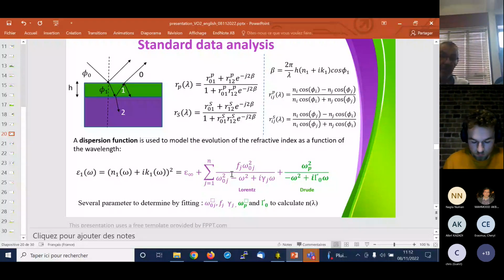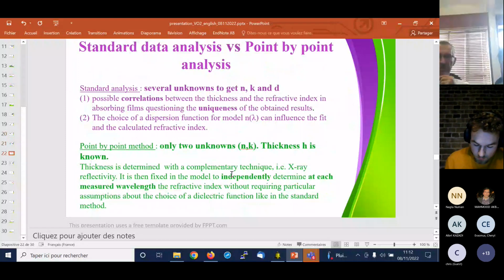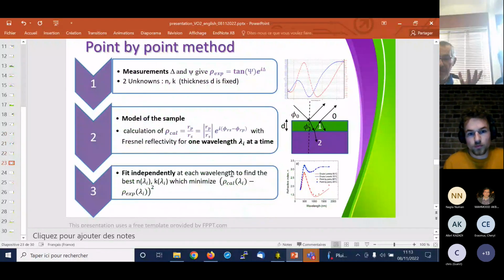And so the story which was pointed out by one of the referees, when we wanted to publish this paper, the referee said, well, you should not do that. You should do the point-by-point method. And the point-by-point method is indeed a very good method because you don't need to describe how the index of refraction is changing as a function of wavelength. You just have 2 measurements, delta and psi, and you have 2 unknowns, which are n and k. And with 2 measurements and 2 unknowns, there is only one possibility to get n and k.